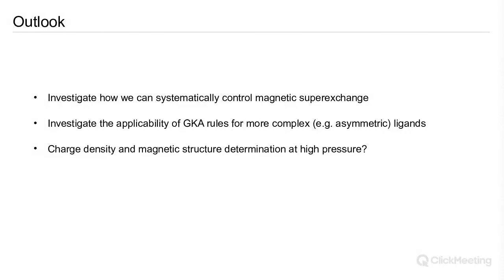And this can occur in one of two ways, actually. Either you can have a material that is polar that magnetically orders, and then the magnetism inherits some signature of the polar domain that it lives in, or you can have systems in which the magnetic structure itself breaks inversion symmetry and thereby directly couples to the polarization. And there is some interesting work being done on very similar frameworks to these, actually. So if you have manganese and cobalt, methylammonium as an A-site countercation, there's some work being done in this direction.